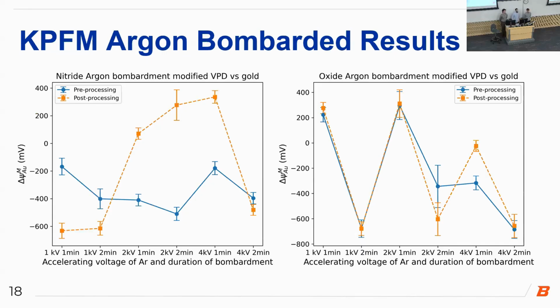What the heck is that right-hand side telling me? First of all, what's my y-axis? That's the voltage potential difference versus gold. All of our KPFM samples were measured against a standard of gold. The main issue with using KPFM for these electrical tests is that this is done not only in air, but also against a reference. So this is not strictly a quantitative value of exactly what this sample is. This is against a reference of gold.